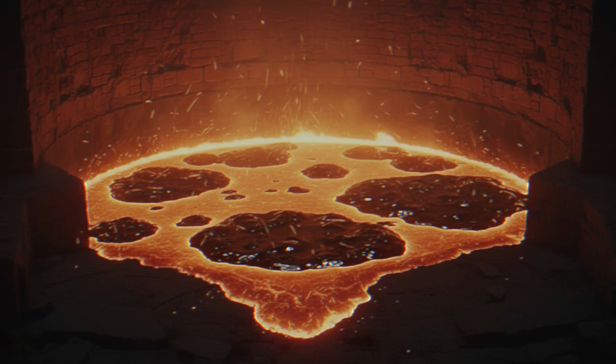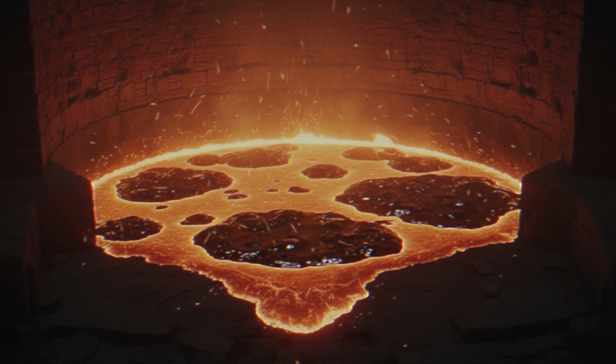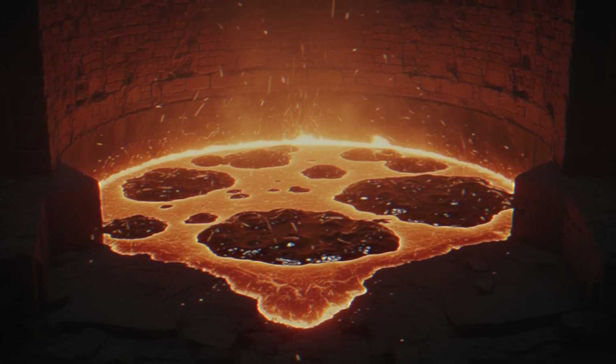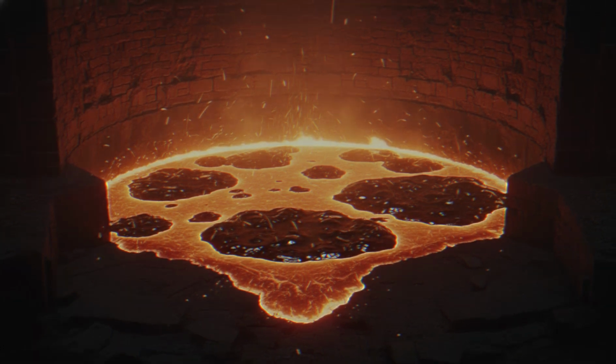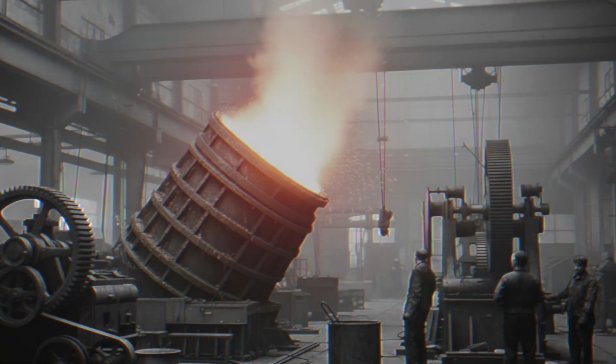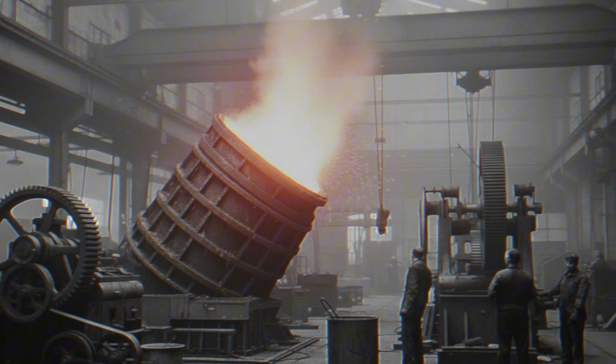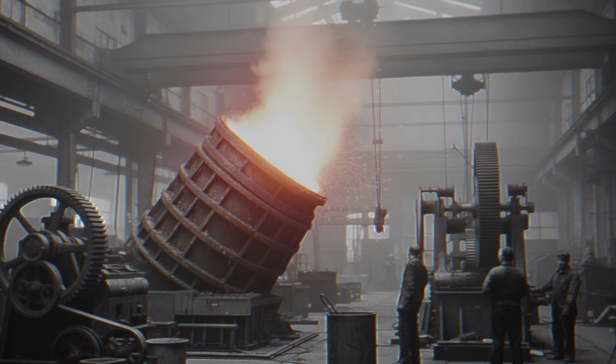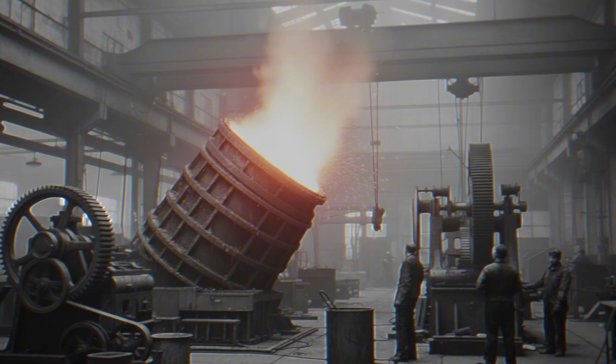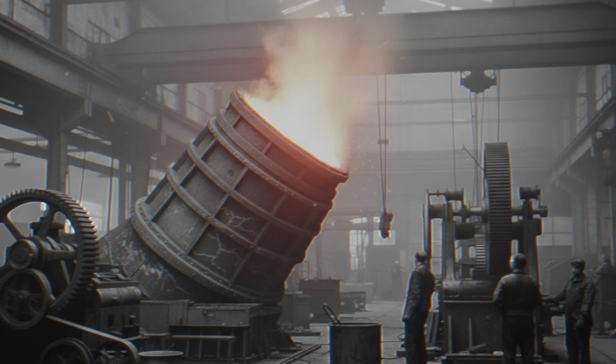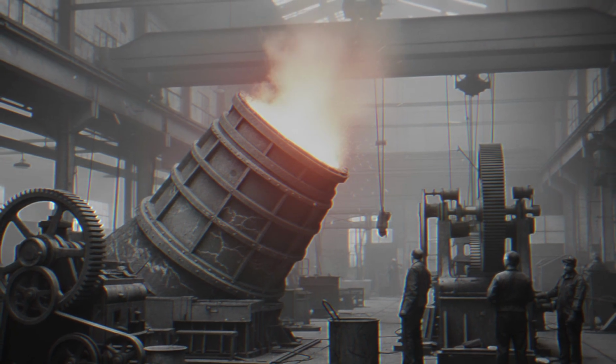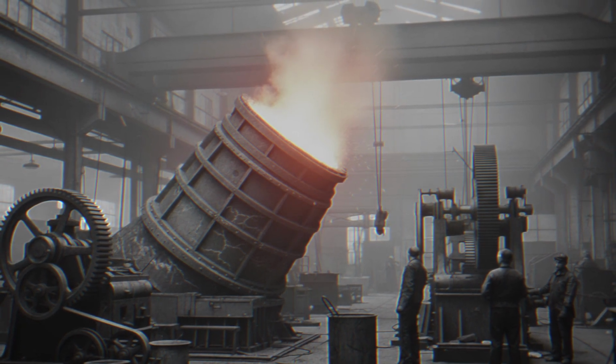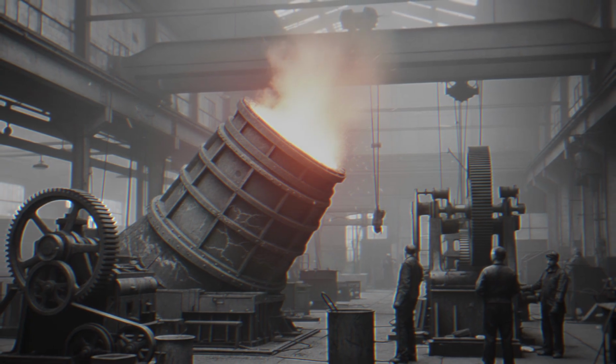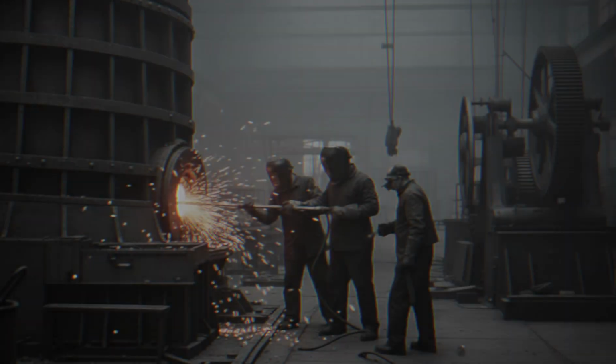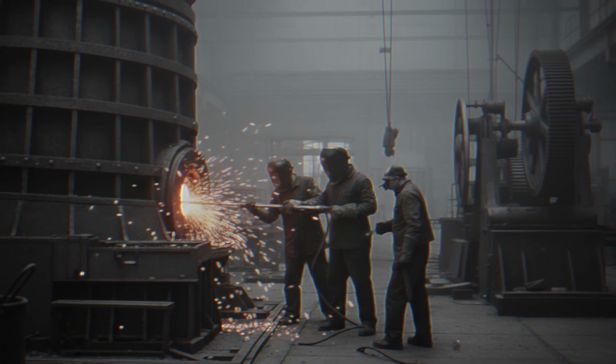When the tap hole broke through, iron, at approximately 1,450 degrees Celsius, flowed outward under hydrostatic pressure. The flow rate of a typical cast was roughly 3 to 5 tons per minute. If the iron trough had water in it, from rain, from leakage, from improper preparation, the contact between molten iron and water produced a steam explosion. The technical term is a steam explosion because that is what it was physically, water converting to steam faster than the surrounding environment could contain the pressure of the phase transition.